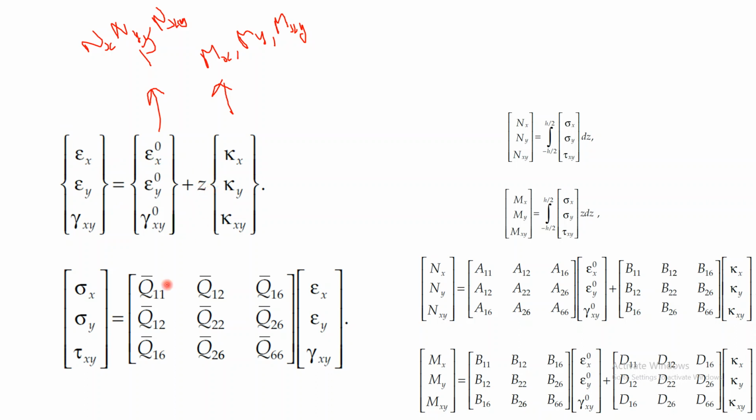That's it. Okay, and usually the strain is not our important criterion. We are always interested in the stresses developed in the lamina. So if you want to calculate the laminate stresses, it can be denoted by this equation, and you are familiar with this. So here I should substitute these epsilon strains into this matrix. If I substitute that, that gives you the sigma x, sigma y, tau xy. And later on, so these are all the forces, right? Nx, Ny, and Nxy are the forces, and Mx, My, Mxy are the moments.